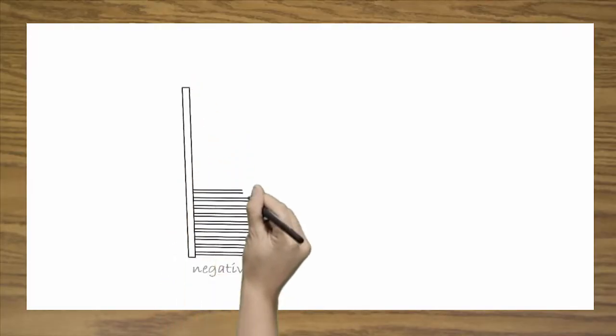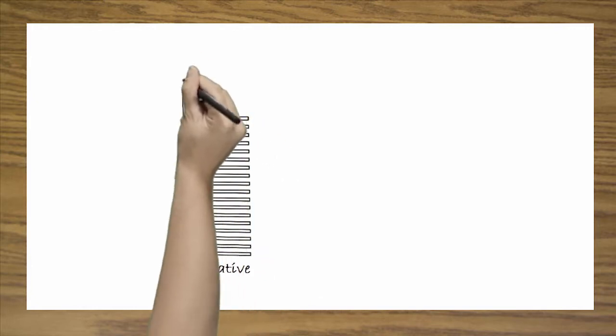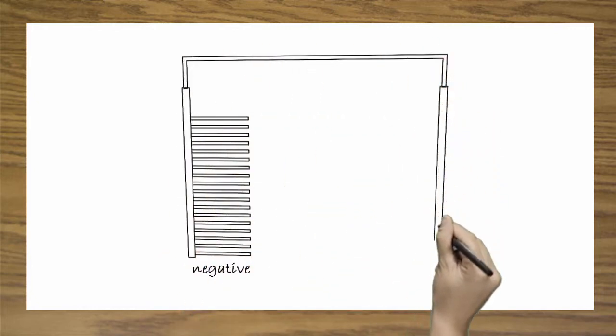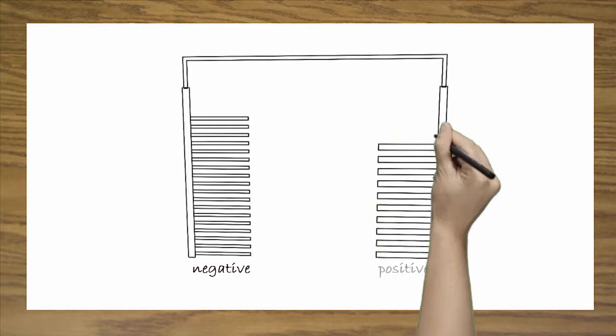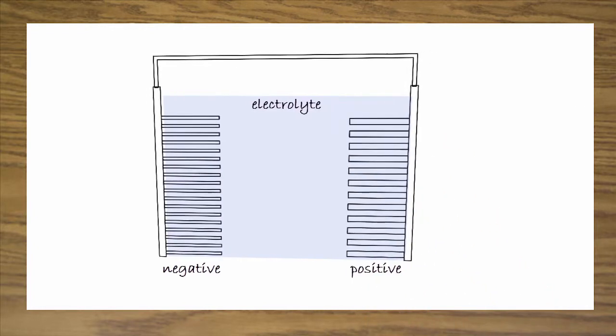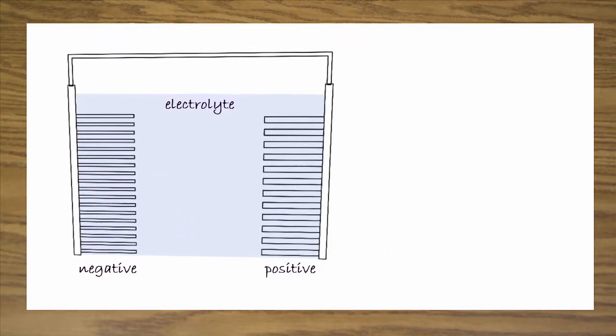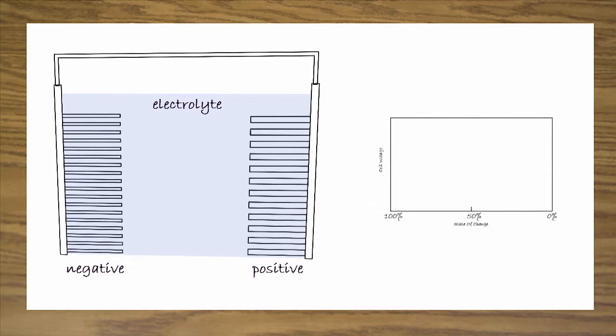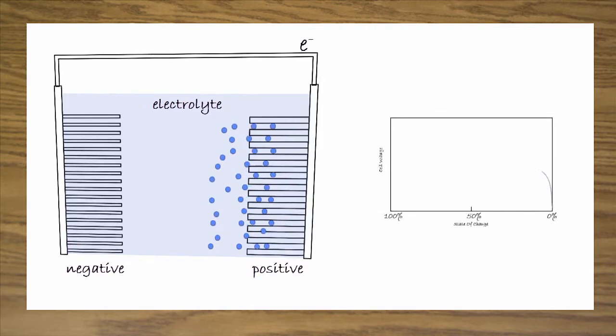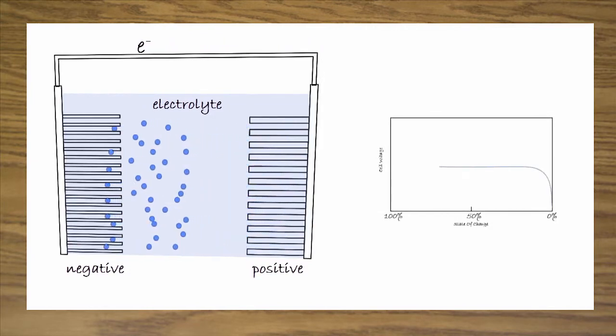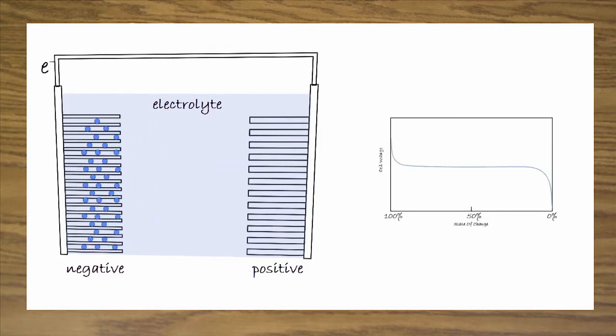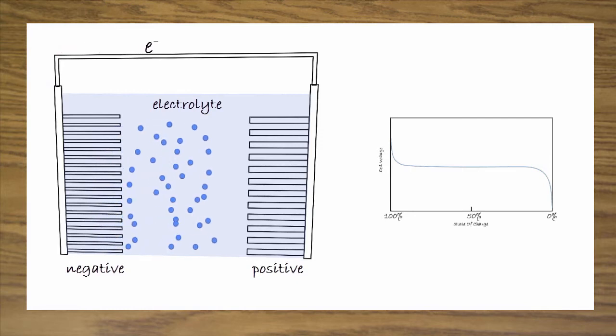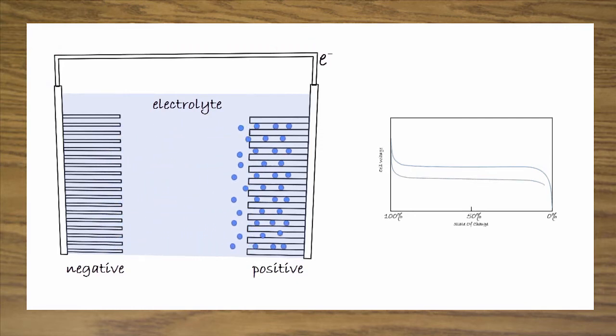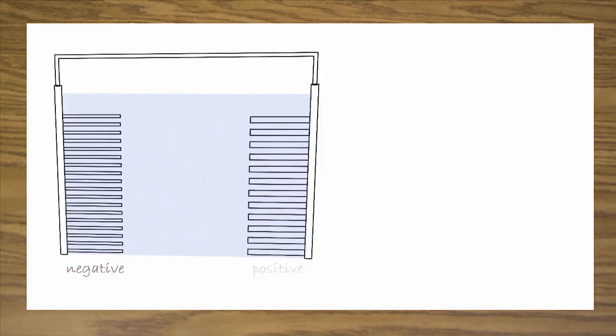In a simple way, a lithium-ion battery is constituted of a negative electrode, generally graphite, and a positive electrode, such as lithium cobalt oxide, separated by an electrolyte, which consists of a salt dissolved in organic solvent. During charge, lithium ions are deinserted from the positive electrode, migrate through the electrolyte and insert at the negative electrode, while under discharge, the contrary occurs. Simultaneously, electrons pass through the external circuit, producing current.